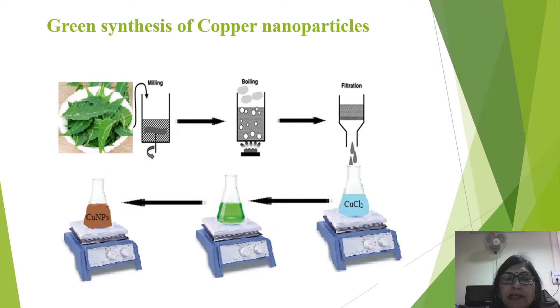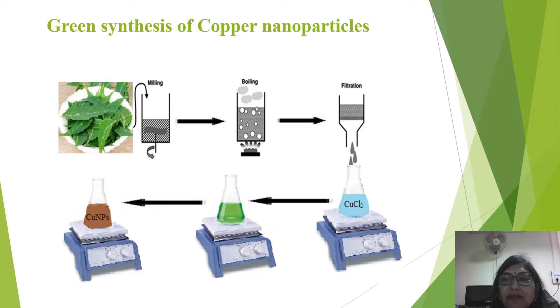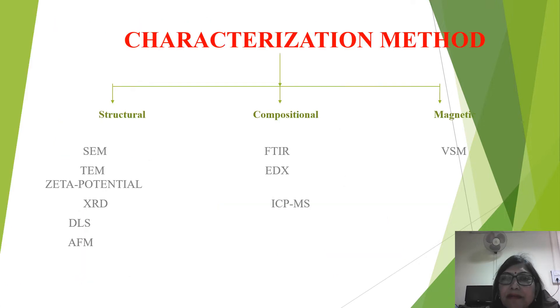Here I am presenting the synthesis of copper nanoparticles using the green route, in which we use the Azadirachta indica extract, which is added into the copper salt dropwise. As time passes, the colour of the dispersion changes from blue to green and finally changes to brown and dark brown colour, which indicates the formation of the copper nanoparticles.